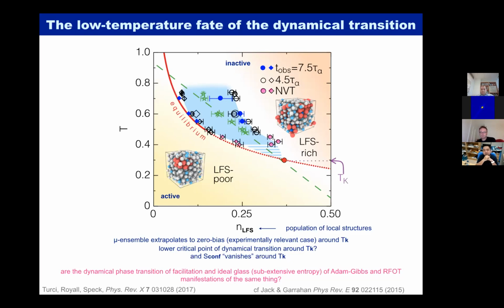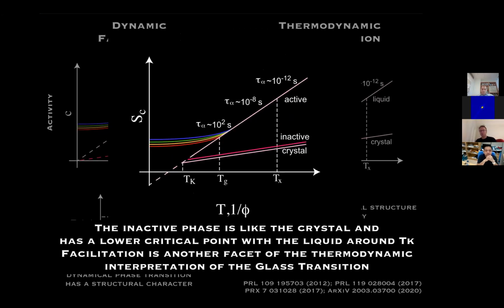Okay, fine. But another thing, if you think about it, is why another critical point, if there is one, is near the Kauzmann temperature. So this boils down to the configurational entropy of the structure-rich state, and that turns out to be rather low. Because this configurational entropy of the structure-rich state is rather low, then inevitably it's near the crystal. Of course the crystal has a very low configurational entropy, so they can't avoid being close together. It's really a question of how close. So actually, I said that this darker red line should be bounded by the Kauzmann. It turns out it does depend on the model. It's more or less close to the crystal depending on the model, and also there's a little bit of speculation here because a crystal in a Kob-Andersen model is not straightforward, but we're looking at that.